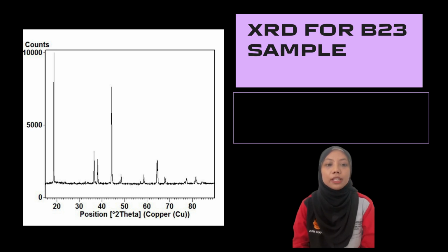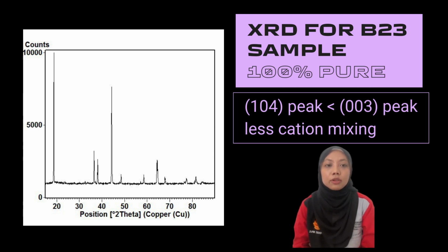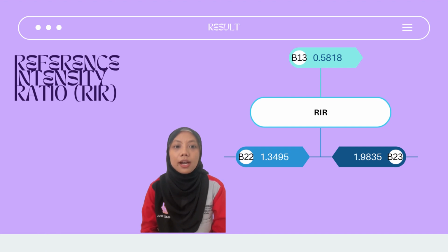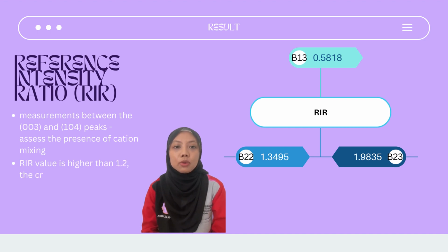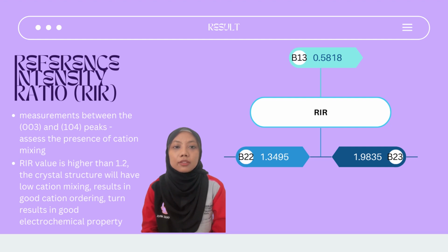XRD patterns reveal that only the B23 sample was 100% pure, isostructural to the LiCoO2 crystal structure with the ICDD database pattern. The 104 peak is shorter than 003, indicating that there is less cation mixing present in the crystal structure. Reference intensity ratio (RIR) measured between the 003 and 104 peaks was used to assess the presence of cation mixing. It is reported that if the RIR value is higher than 1.2, the crystal structure will have low cation mixing, which results in good cation ordering, which in turn results in good electrochemical properties.